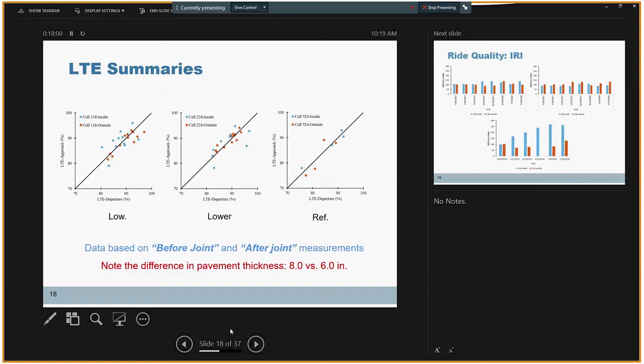Comparing the data for the two experimental pavement cells, cell number 138 and 238, we had really comparable performance for these two pavement types, regardless of the binder content. The LTE values were ranging from almost 80% to 95-97% for these two concrete types. And it's interesting to see that there is a slightly higher scatter while comparing the LTE values for the approaching and the departure traffic for these two concrete mixtures for the lane exposed to traffic load. But for the outside lane, which is not exposed to traffic, the departure and the approach traffic loads were, I would say, more comparable. We had a lesser extent of variation in these two.